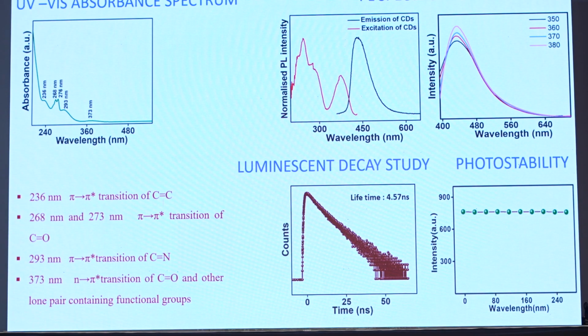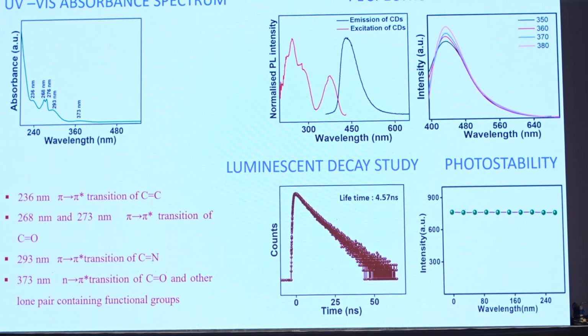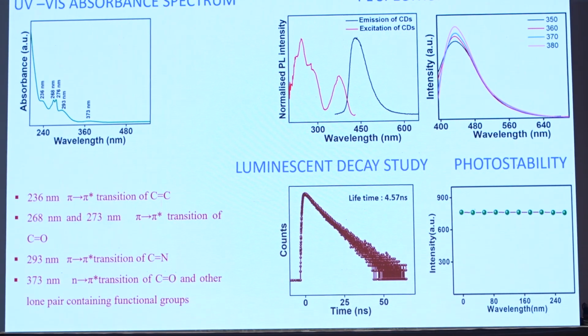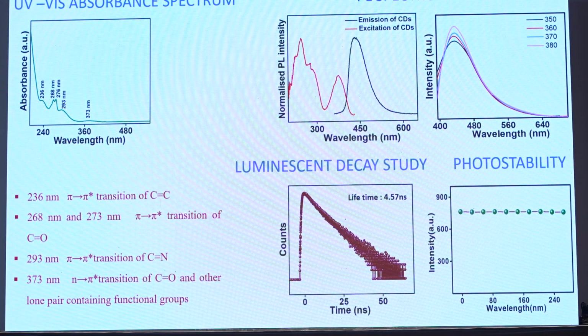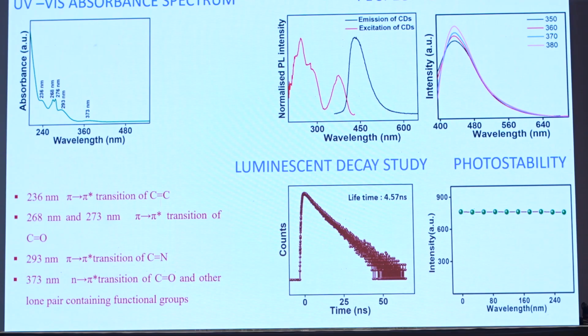UV-visible spectroscopy shows that it contains 5 peaks, one at 236 nanometer corresponding to pi to pi star transition of C double bond C, and the peaks at 268 and 273 nanometer correspond to pi to pi star transition of C double bond O, and the peak at 293 corresponds to pi to pi star transition of C double bond N, and the peak at 373 corresponds to n to pi star transition of C double bond O and other lone pair containing groups. The PL spectrum shows the excitation and emission spectrum of the carbon dot, with excitation at 350 nanometer and emission obtained at 436 nanometer.